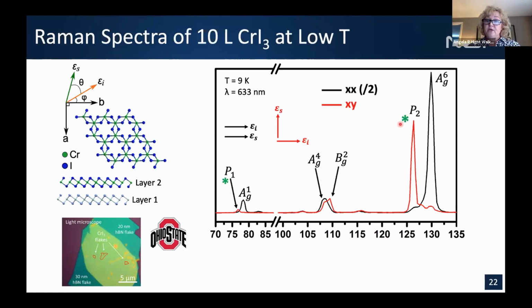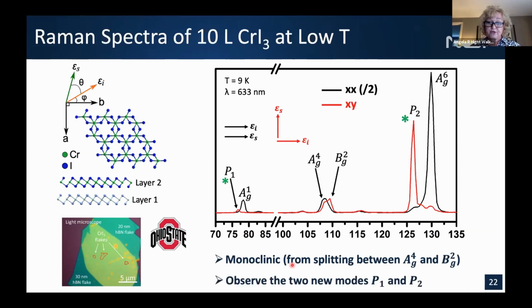Also of note, we see the P1 and P2. I'm calling them P for peak, because these are the features that were called out in the previous paper in the Nature Communications I just mentioned that were referred to as magnons. So I'm just calling them peaks for now as we study what they are. So it's monoclinic for sure, and we observe those same features that they saw. And that paper from Michigan was looking at few layer as well. So this 10 layer behaving like the few layer limit was an interesting thing for us and a bit unexpected.